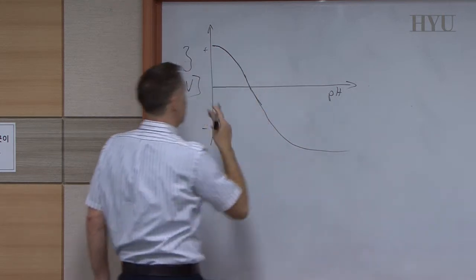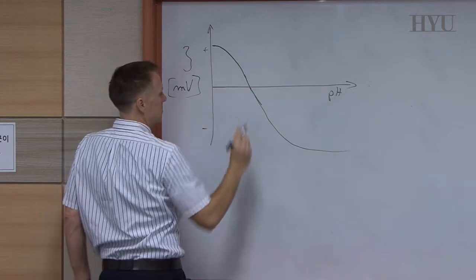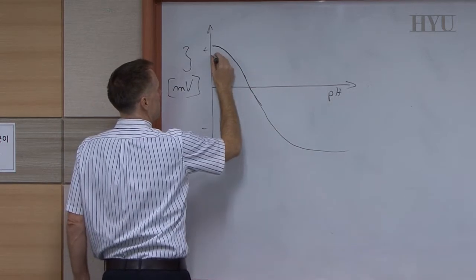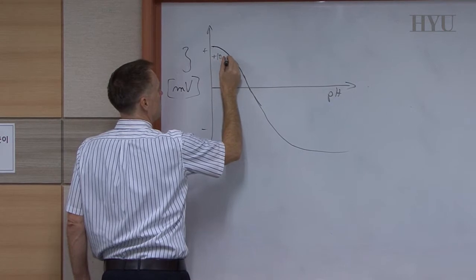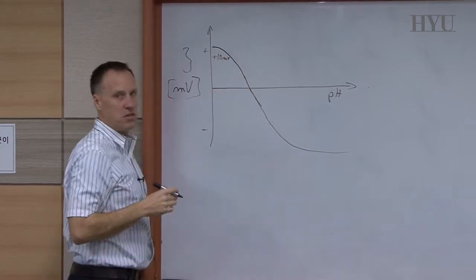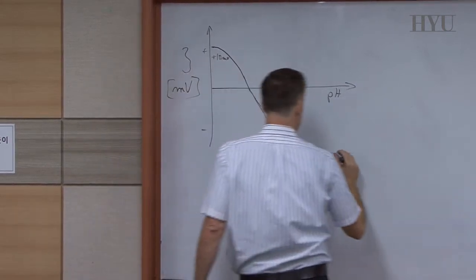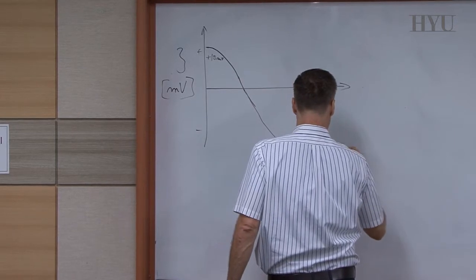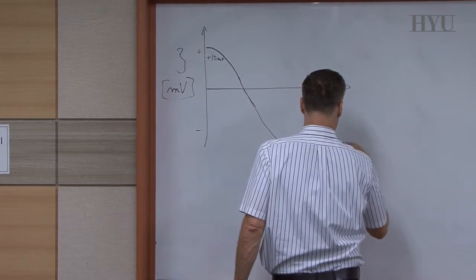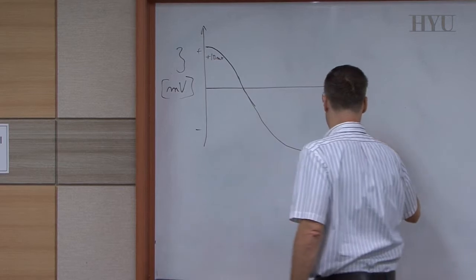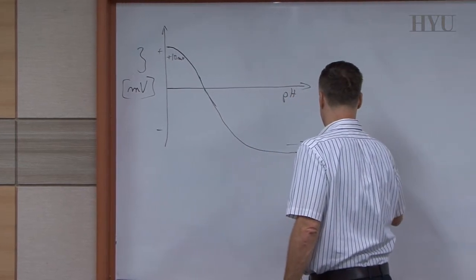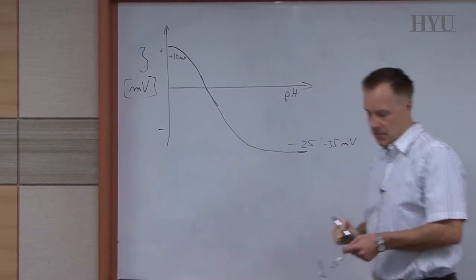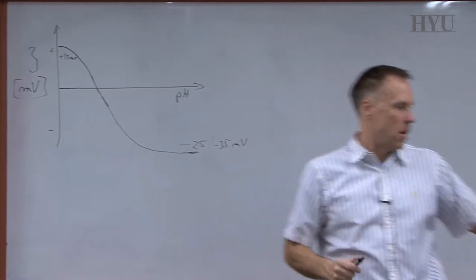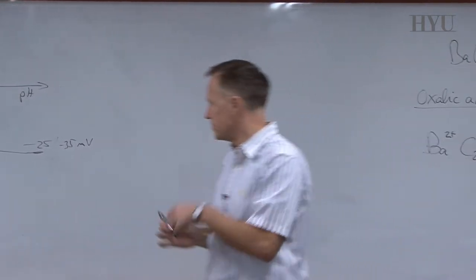So the positive range here is around plus 10 millivolts or so, plus 15 for barium titanate. It's usually not very high. And the negative part is around minus 25 to maybe minus 35 millivolts for barium titanate. It's never really high. And why is this the case?